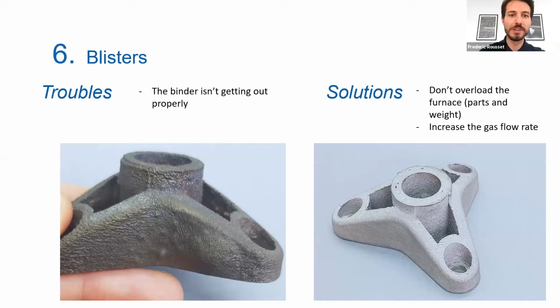Yes, of course. So the blisters are quite common on most printers, or even in injection molding. It is happening quite a lot. We have a very good solution for this that is working very well. If you have a lot of parts inside the furnace, you have a lot of binder that you have to get out. So try to not overload the furnace, and try to not have parts that have a lot of weight, because you have a lot of binder to get out, and this is quite hard. This is what makes a lot of blisters on your parts.